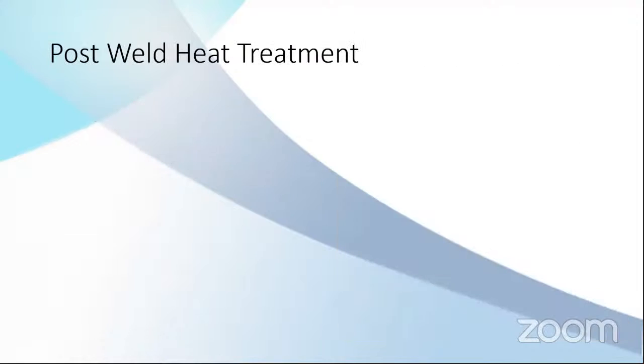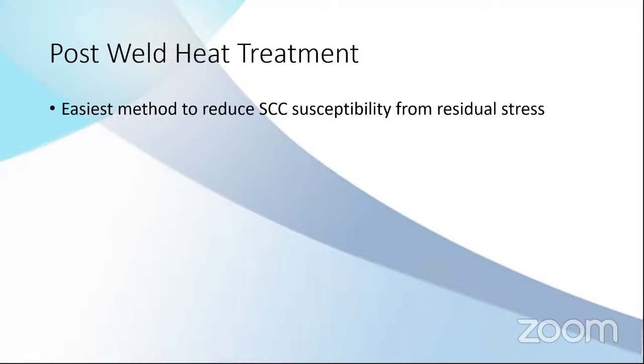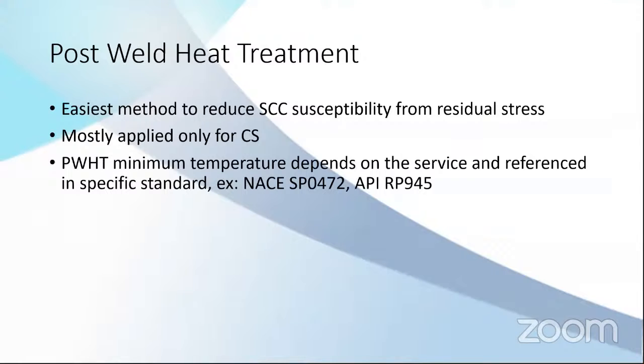Now about post-weld heat treatment. This is commonly done to avoid stress corrosion cracking because it reduces the residual stress level in the weldments. It is mostly applied only to carbon steel. When you apply it to stainless steel, it will cause another problem. Like I said, post-weld heat treatment is around 600 up to 650 Celsius, so it's in the sensitization temperature range. So normally we avoid it for stainless steel because it makes it susceptible to other corrosion problems.